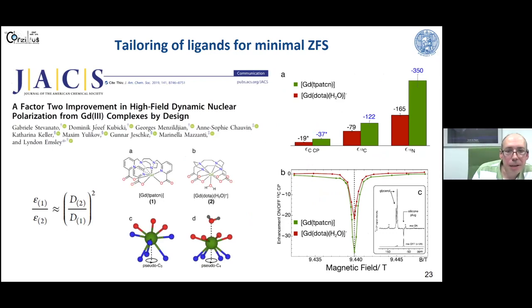You can design practically complexes or ligands with higher symmetry. And if you do this, you get actually a boosted gain of the enhancement, because I've already mentioned that the second order effect scales as the square of the zero field splitting constant. So if you reduce your zero field splitting constant by about a factor of 1.4, you get a twofold increase in DNP enhancement. This has been shown by a group around Emsley recently.